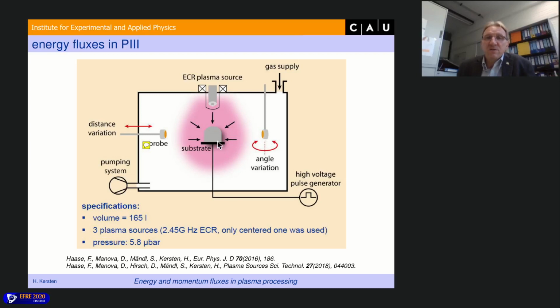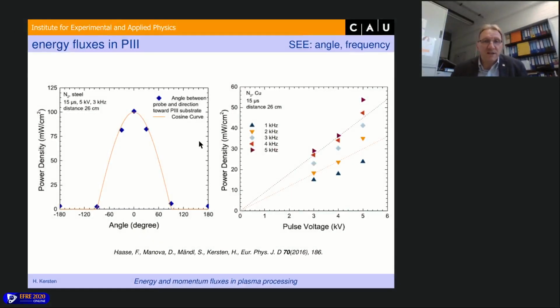And as you know, during PIII, you have a short, very high negative pulse. And that means for a short time, you have a matrix sheath in front of the substrate. All electrons are depleted, and the ions are more inert than the electrons, so they stay for a certain time in the sheath, and then they are accelerated by the high negative pulse into the substrate, and so they are implanted, for instance, nitrogen ions. This is the principle of the plasma ion immersion implantation.